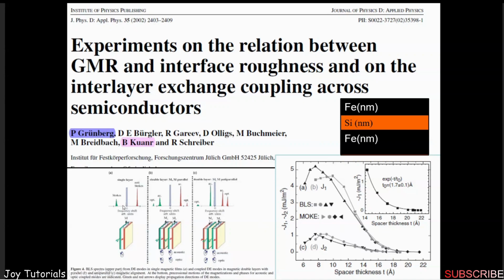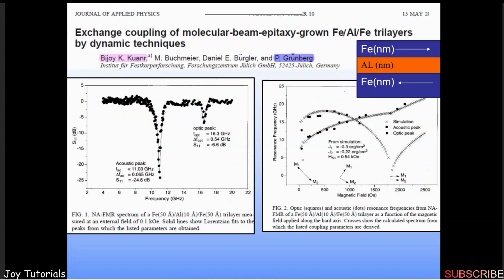The theory behind this is Brillouin light scattering, where there is the Stokes and the anti-Stokes spectrum. From this, one can see the optic and the acoustic mode. There is the in-phase precession and the out-of-phase precession of the magnetization in the tri-layer or the multi-layer structure. Here, the microwave technique is used to show how the exchange coupling of a molecular beam epitaxy iron